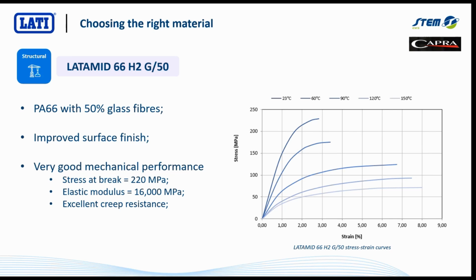that we need for this application. Just a note, you might be thinking, well, okay, why don't we use carbon fiber rather than glass? Too brittle for an application like this, really. So if we want the good impact performance, then typically glass has got better impact performance than carbon. So that's the material. Glass is the reinforcement that we need for an application like this. And for a nylon 6/6, it's got relatively low moisture uptake, this material.